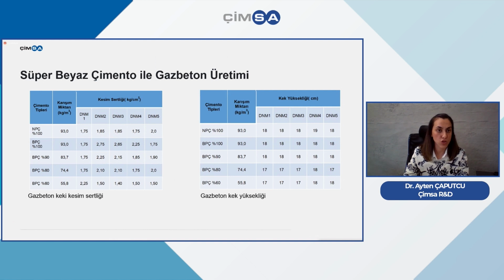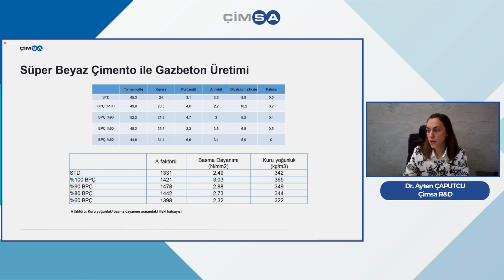And when we look at the following tables as well for cutting strength, with different levels of solidification, this is a factor also emphasizing the relation between the white cement and a standard Portland cement. And we see that there is a resistance when using white cement. And we see from the screens and the values that we can reduce the amount of cement overall up to 20% while using super white cement as well.